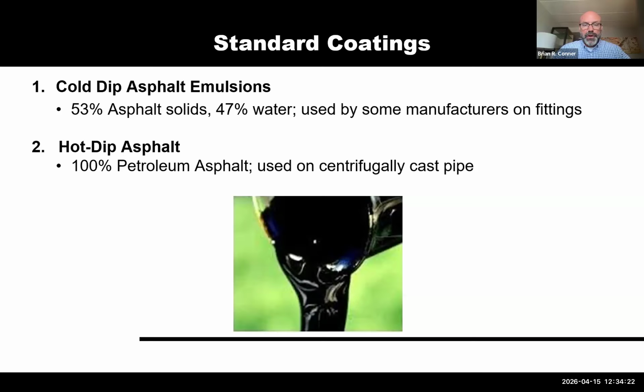There's no chance for dirty smudging of the asphalt or anything like that. Charlotte Pipe is the only manufacturer of cast iron pipe and fittings that uses that technology. But we have been doing that with all of our fittings now for 10 years. Now, on the pipe side of the business, 100% of manufacturers are using a hot dip asphalt. It's a petroleum asphalt, and it's used on the centrifugally cast pipe. It's essentially dunked into an asphalt bath, and that's what's used to cover cast iron pipe.